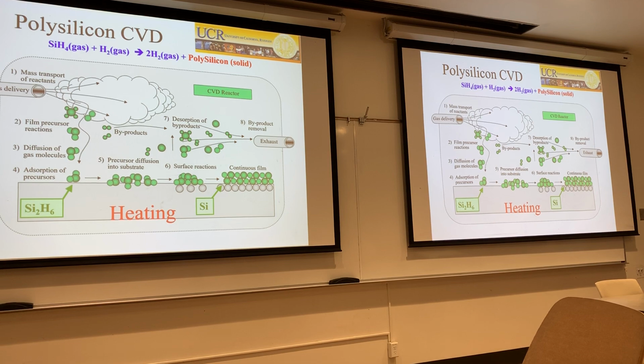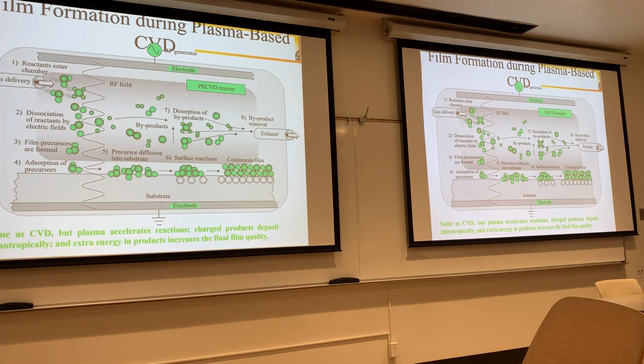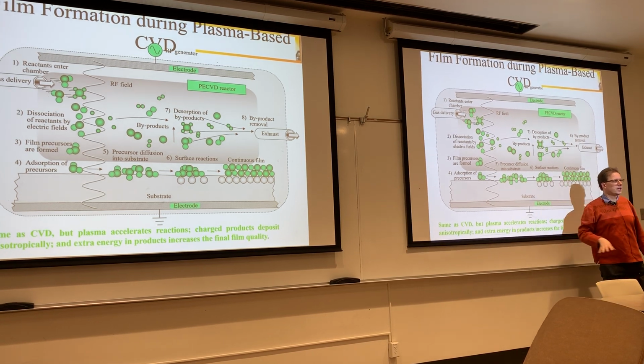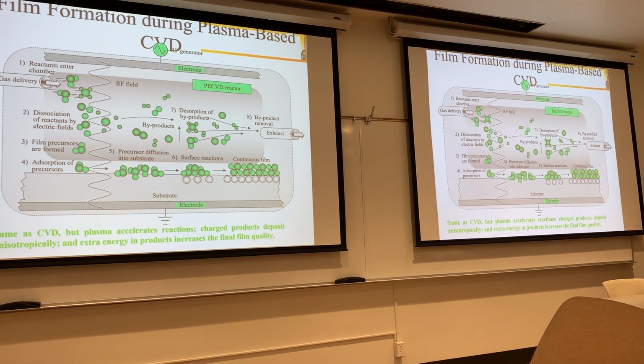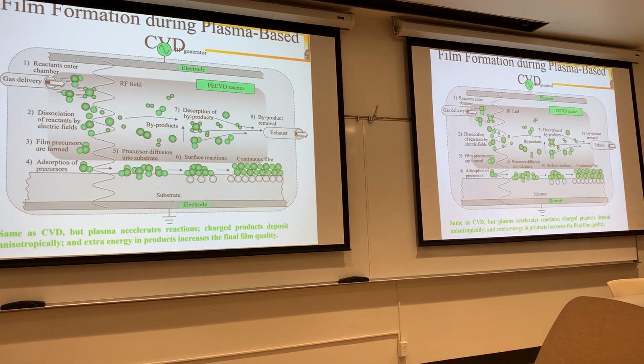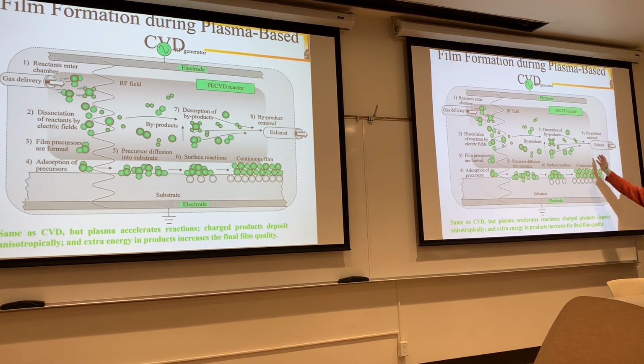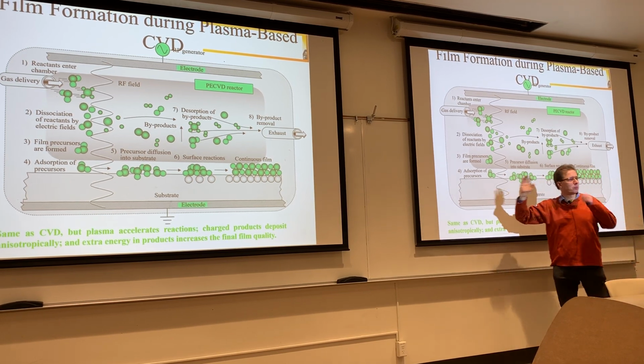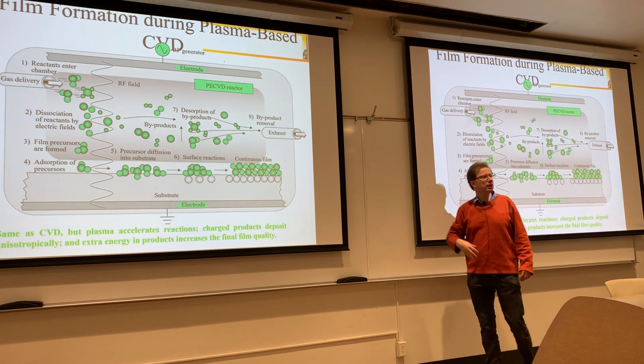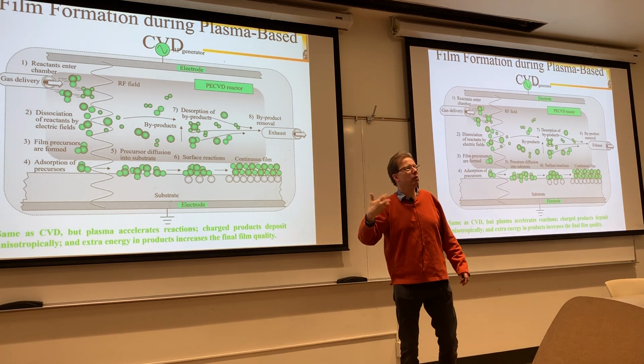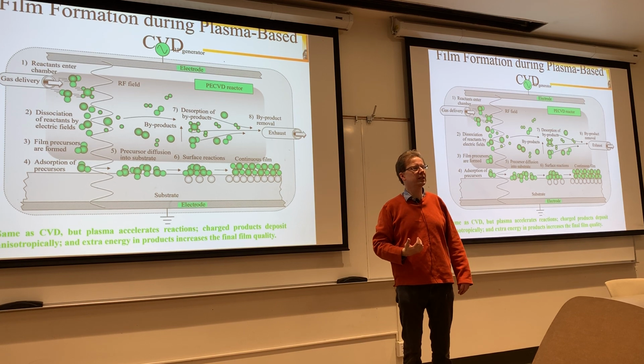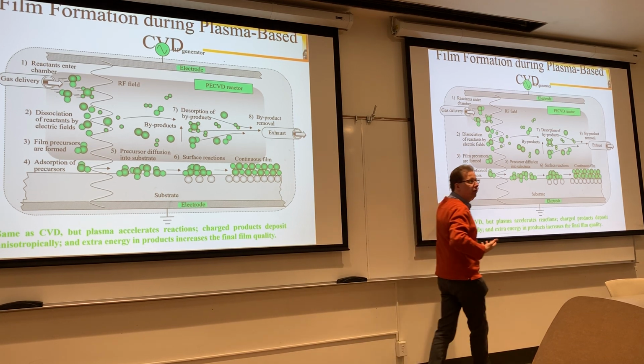decompose and form silicon. Very frequently you do it plasma-based, where you create a plasma in the gas phase, where electrons are separated from molecules, not all electrons, but maybe 1 or 2 per molecule. And as a consequence, you can activate or break bonds in the gas phase very easily. So you can activate it so that one of the hydrogens falls off the silane. And so once it comes on the surface, it is more reactive and you will have a quicker growth on the surface.